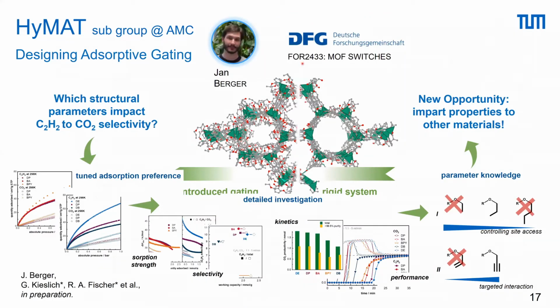So this is integrated in the research unit 2433. It's called MOF switches. And here we integrate gas sorption selectivity into certain metal organic frameworks. This is again such a hexagonal system, which is essentially a rigid one, but the flexible property comes from the dangling side groups. These are side groups of different length and chemistry, so this would be saturated or unsaturated side groups of different length. And we could show that if you put in these ones or these ones, they enhance the selectivity of the gas sorption of the system.